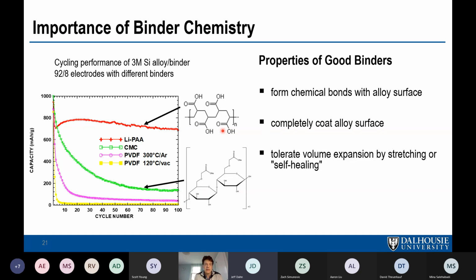You can't do that by spin coating. So if you want to measure the electrochemistry of a binder, you have to take an inert material like titanium nitride and coat it like a regular coating with the binder. And then all the electrochemistry is this 15 to 20 angstrom thick layer on the inert particles. And then you can see the voltage curve of polyimide and that it is indeed decomposing to disordered carbon. I remember all this now that you've reminded me, and it's a great story for everybody else to listen to. It's really kind of cool.